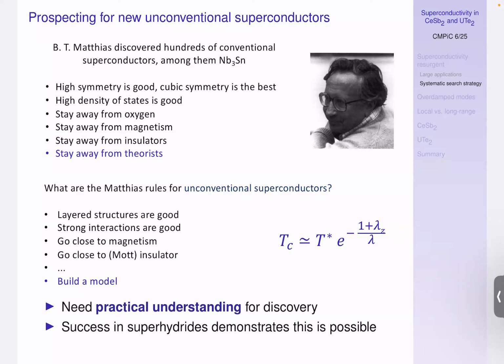And we know that this is possible because the superhydrides work was largely done that way. Because if you're looking for new superconductors at millions of atmospheres, you can't do high throughput screening. You have to have a fairly good idea what you should try. So there was a very strong interaction between computational modeling and experiment in that field. Of course, it's easier because they're conventional superconductors, so you have a very good, very advanced mature theory to use. It's much harder to do in our field.